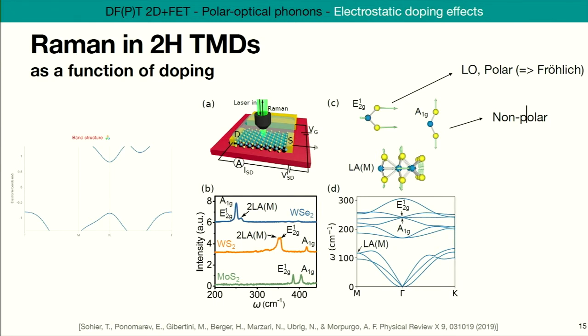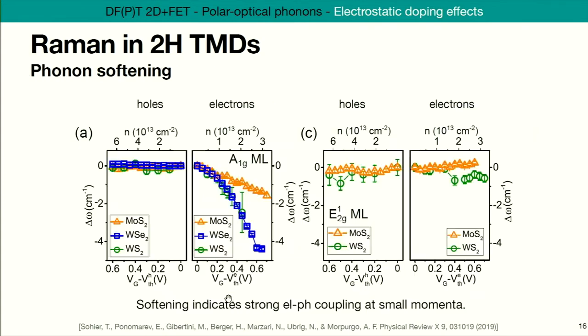And in Raman spectroscopy, essentially you get peaks, and those peaks are situated at the frequency of vibration of the phonons. So it's a pretty direct way to study phonons. And here, in this case, you can study phonons as a function of doping in situ as you dope the system. So very nice setup. Another nice thing about this experiment is that they didn't do it only for one TMD. They did it for three, so WSe2 that we see here, WS2, and MoS2. And they get this very consistent result.